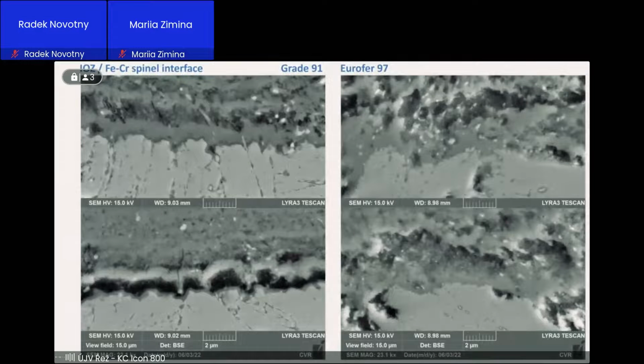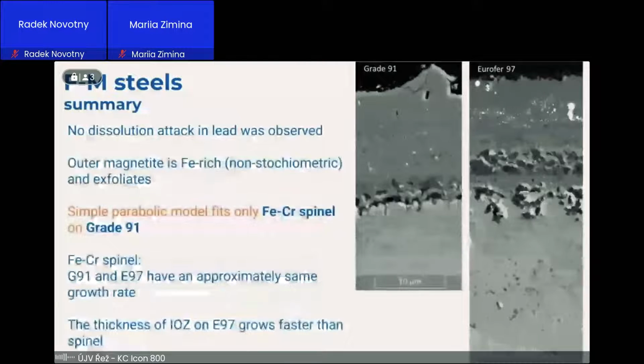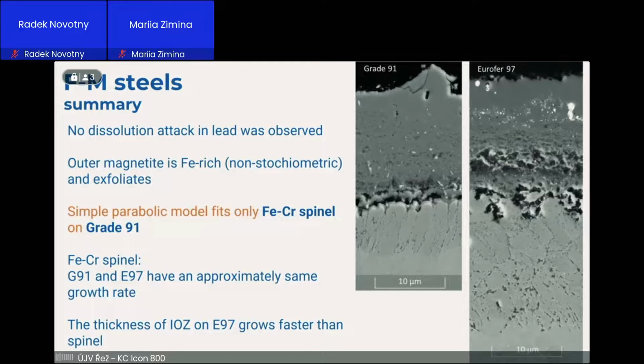So the difference between Eurofer and grade 91, both are 9% chromium steels, they should behave similarly, is the formation of this very thin layer between the spinel and internal oxidation zone interface. That Eurofer is unable to form. The explanation I don't have. So the summary, the spinel is probably responsible for this corrosion resistance. Both steels exhibit high temperature oxidation. You can see that Eurofer has a very large internal oxidation zone.